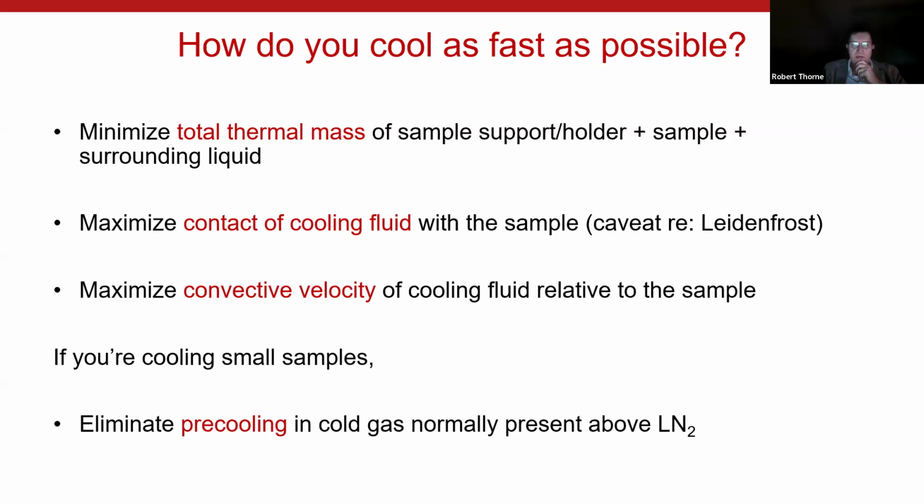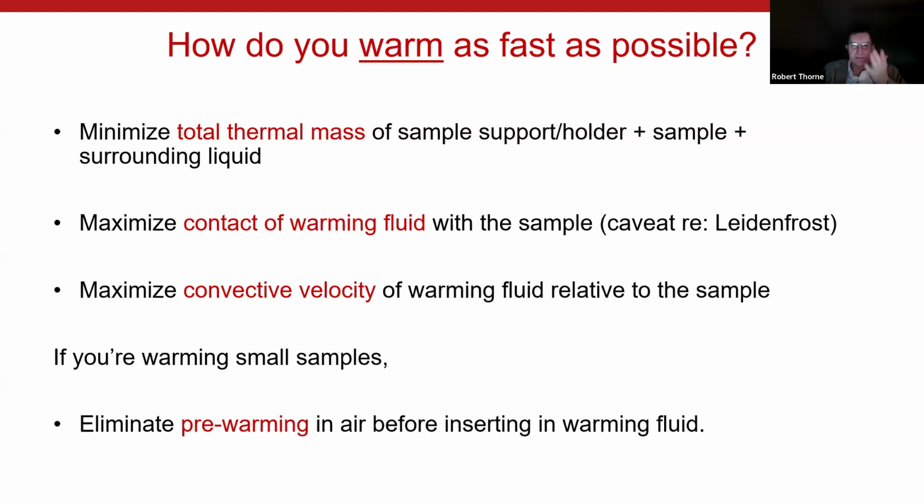Okay, so that's how you cool as fast as possible. How do you warm as fast as possible? Well, it's all the same principles. Minimize thermal mass, maximize contact of warming fluid with the sample, maximize convective velocity, and eliminate pre-warming in the air before you insert it in the warming fluid. Okay, so there's nothing earth-shaking here. And as theoretical physicists like to say, the rest is engineering. Of course, for us, that's the fun part. And yeah, that's what we've spent a lot of time on.